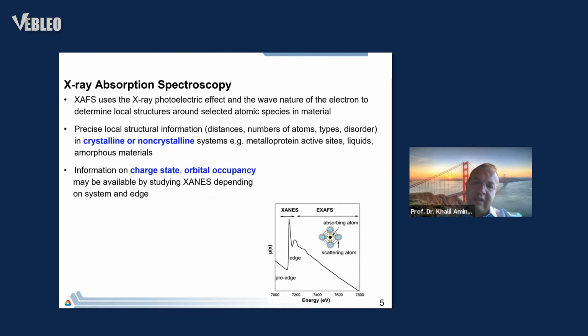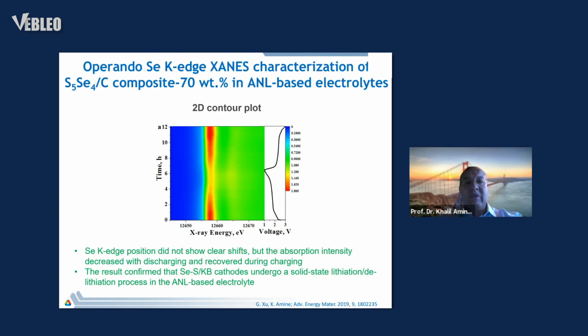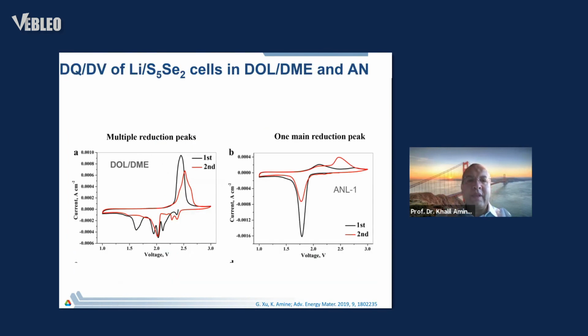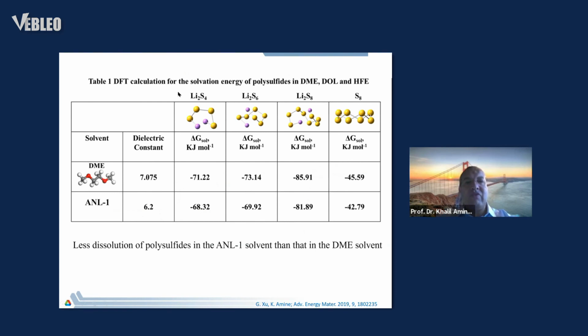So you can discharge your cell and run thousands of spectra to look at any shift due to the change in the oxidation state in the solution. And that's exactly what was done. This is many spectra during the charge and discharge. If you have a dissolution, you get a reduction of the polysulfide, of the sulfur, and therefore you should see a shift toward lower energy. You can see we don't see that shift. We have a flat curve, which is an indication that we don't have any dissolution at all. We also did a dQ/dV that shows that we have one reduction peak compared to multi-step reduction due to polysulfide dissolution.